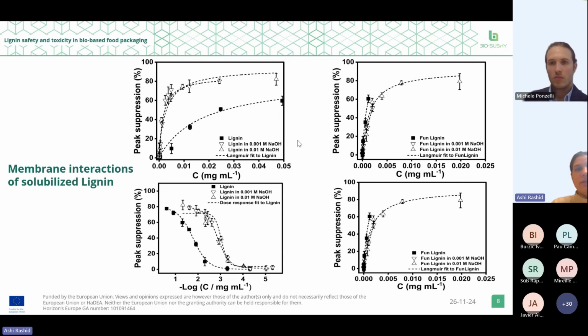For functionalized lignin, we can see there is a difference in membrane activity in the presence and absence of sodium hydroxide, but the difference is not great. We can assume that the lignin surface in case of functionalized lignin has the silane grafting, as Ivana has shown in her presentation. This silane grafting on the surface of lignin has protected the lignin polymer from depolymerization and hydrolysis, which may account for the relatively small difference in membrane interactions between the functionalized and unfunctionalized lignin under similar conditions.